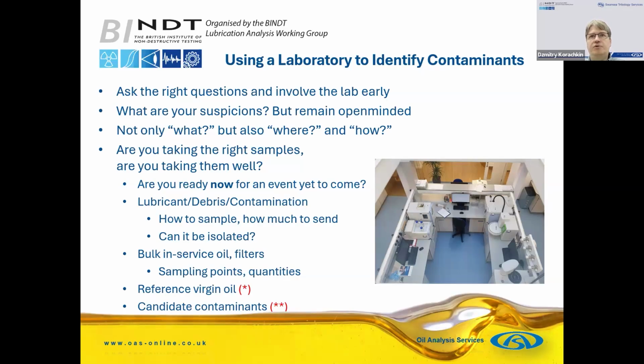So for reference, if there is AdBlue contamination in fuel, if it's significant, there's normally a layer of separated fluid at the bottom of the jar, which you can then test and find out if it's water, something else, or if it's AdBlue. There was no separation there. The sample was black. When we performed the routine analysis, we found trace engine oil additives and a layer of black sediment, likely soot contamination. So it looks like sooty engine oil is getting into the fuel, and that's something the customer can investigate, but it was not in line with the initial assumption of AdBlue.